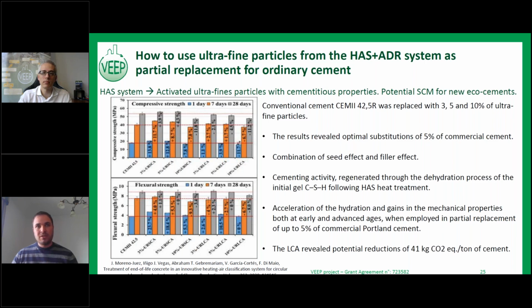For that, we have performed different testing at laboratory scale, manufacturing different samples of standardized mortars, replacing part of a commercial cement. In this case, it was a cement 42.5 with 3, 5, and 10% of the recovered ultrafine particles. We employed two types of ultrafine particles: the first one coming from recycled siliceous concrete waste, and the second one from limestone concrete. You can see the result in this graph, and it was demonstrated that the optimal substitution was 5% of the commercial cement, and we were even able to increase the compressive strength and the flexural strength by employing the ultrafine particles coming from the HAS technology.